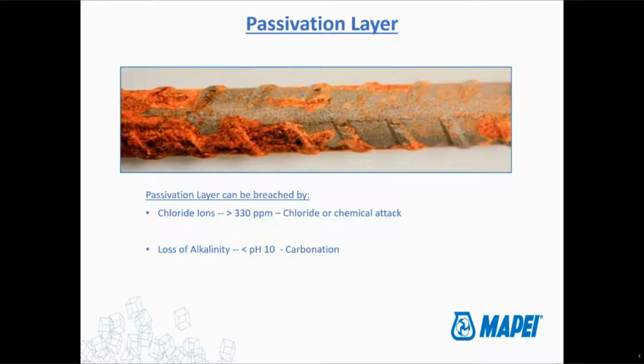So this isn't a combination thing. The passivation layer could be breached either by the chloride ions or by a drop of alkalinity. So if you only have, say, 100 parts per million of chlorides in your concrete, but the pH has dropped all the way to, say, 9.5, the 100 parts per million of chlorides will actually start reacting with the iron at that point because the pH has dropped. So one of these two things is going to happen first. And it's really just a matter of time.